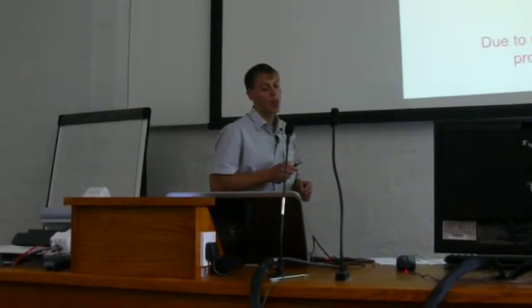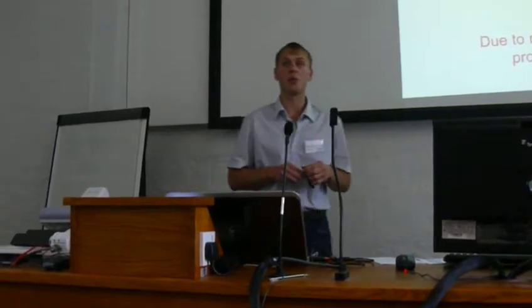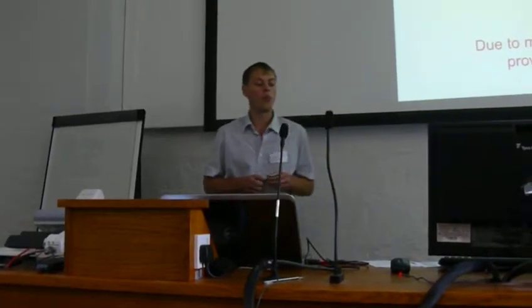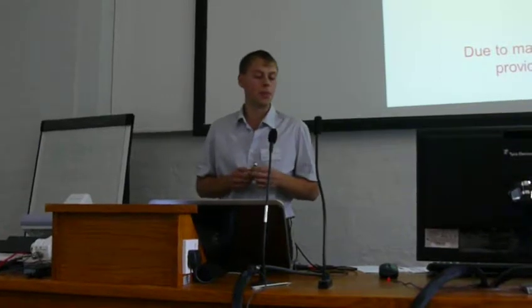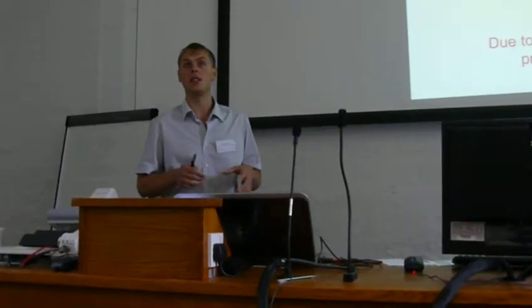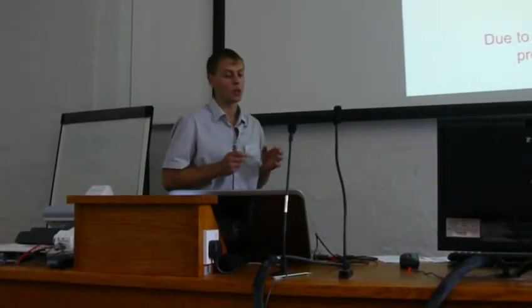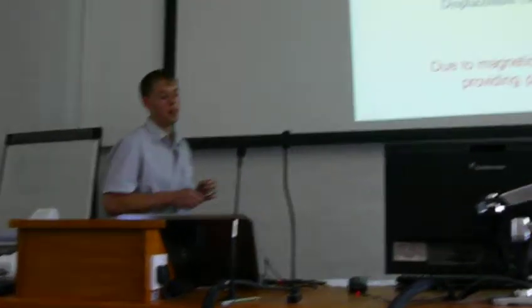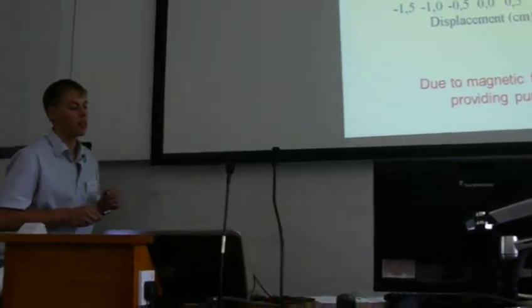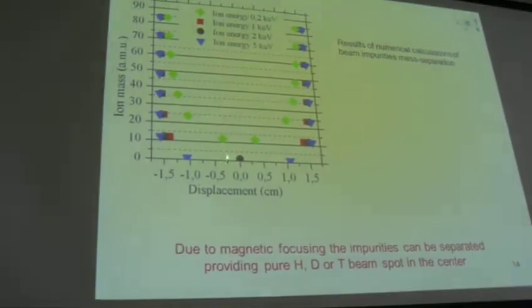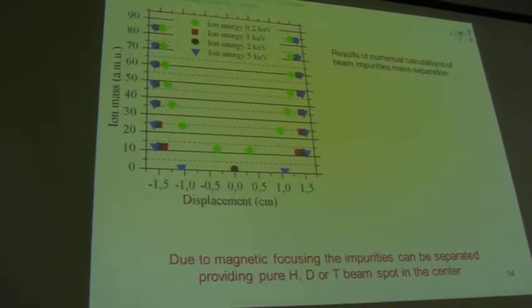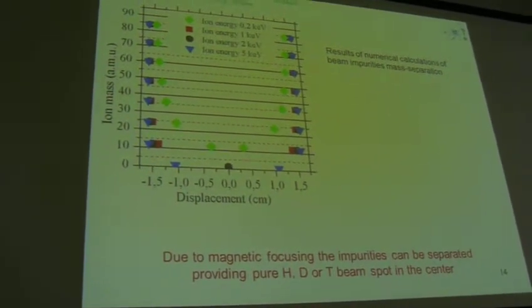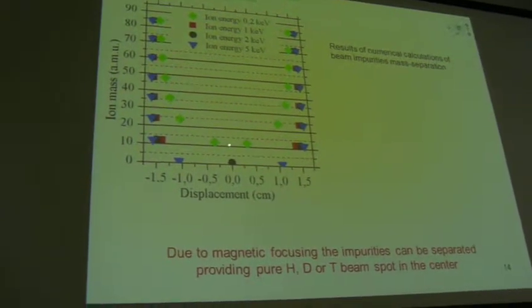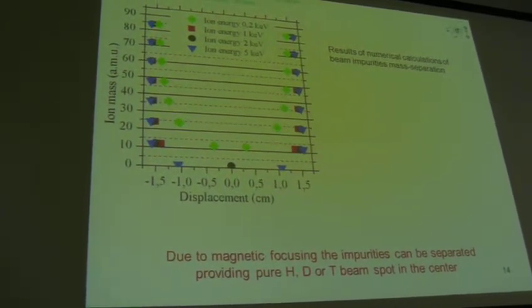This picture shows the result of numerical calculation of ion trajectory deviation taking into account the experimental ion energy distribution function. One can see that the beam impurities are separated to form a circle with a diameter of more than 6 millimeters. And the central part of the spot is free of impurities due to magnetic separation.